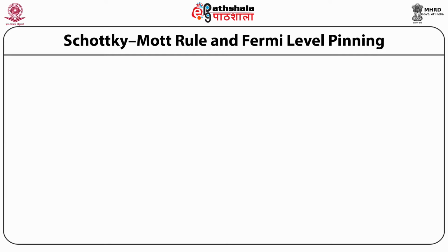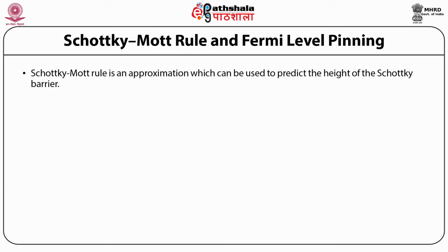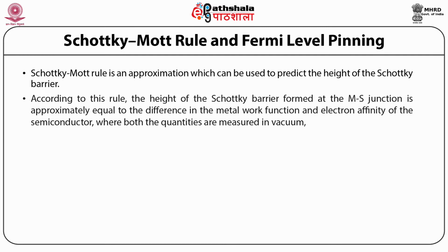Schottky Mott rule and Fermi level pinning. The Schottky Mott rule is an approximation which can be used to predict the height of the Schottky barrier. According to this rule, the height of the Schottky barrier formed at the MS junction is approximately equal to the difference between the metal work function and the electron affinity of the semiconductor, where both quantities are measured in vacuum.